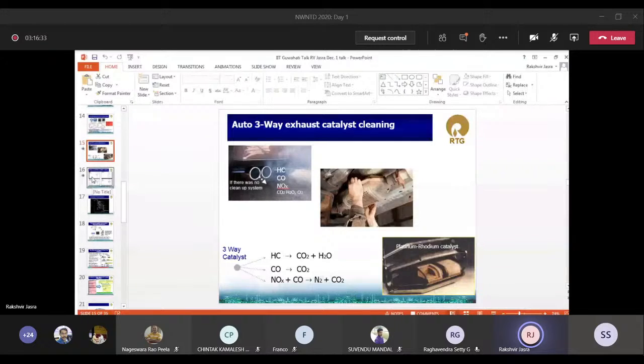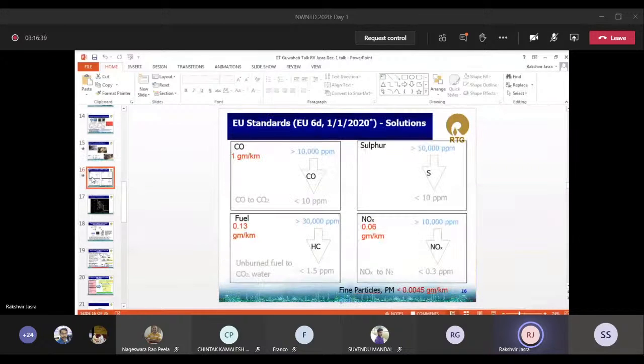Now, I want to show the stringent requirements of this catalyst. This is the European standard, and our Bharat 6 standard is also very close to the European standard. It says the carbon monoxide should be less than 10 ppm. It means most of the carbon monoxide which is generated, which may be as high as 10,000 ppm, should get converted to carbon dioxide. Similarly, hydrocarbon should also go to less than 1.5 ppm, and NOx should go to less than 0.3 ppm. Other two things also are there, sulfur and fine particles, soot. They are handled by different catalysts, but this three-way catalyst only focuses on hydrocarbon, carbon monoxide, and nitric oxide to nitrogen. You can see the demands.